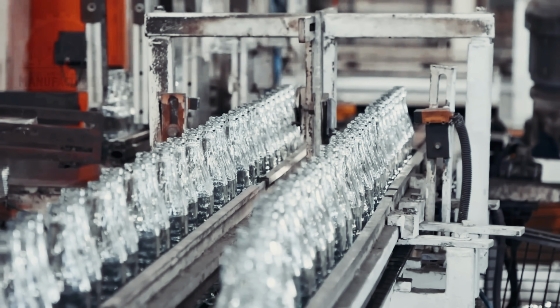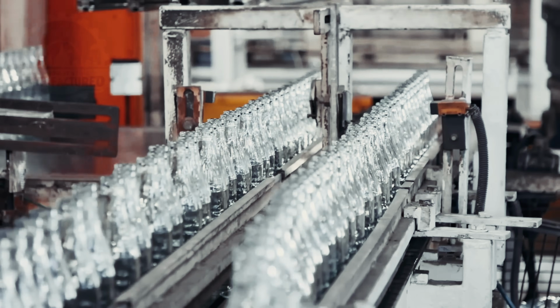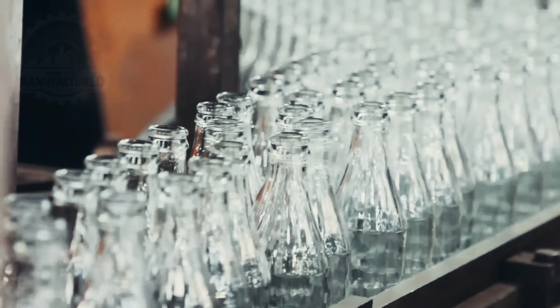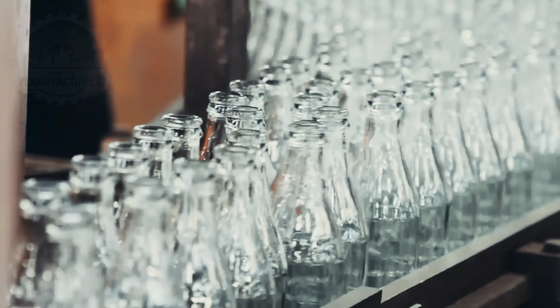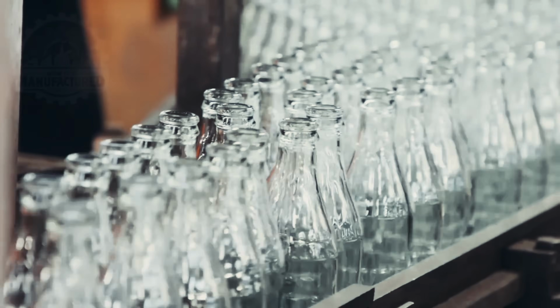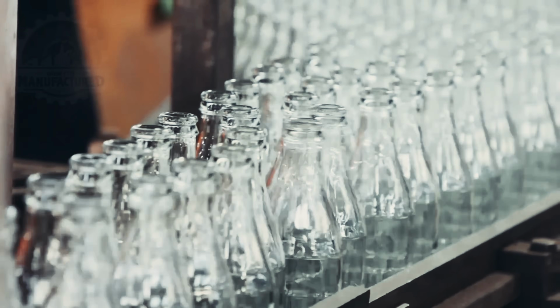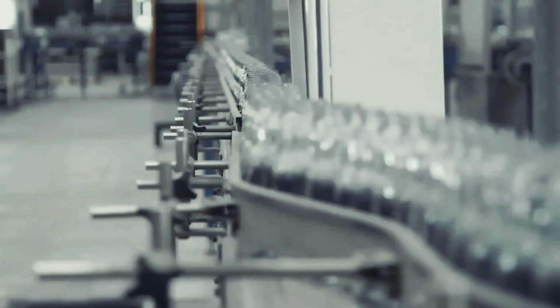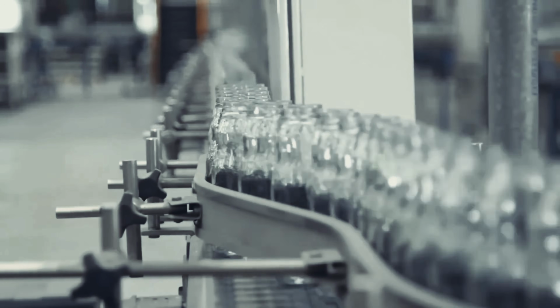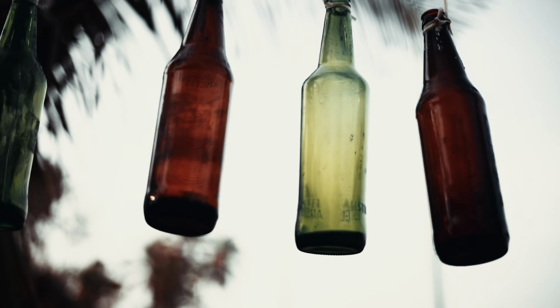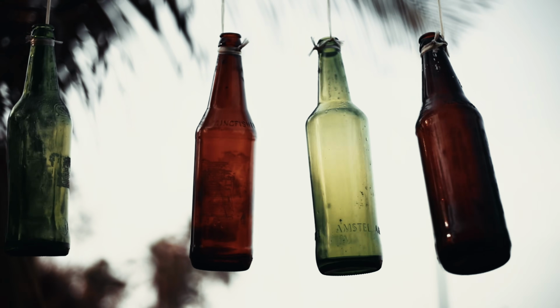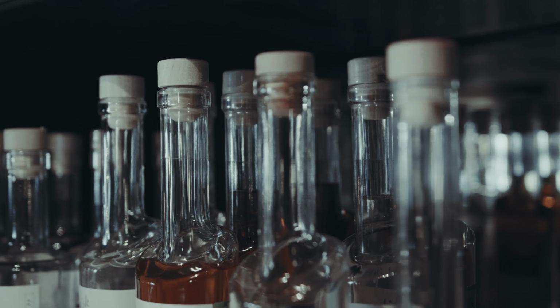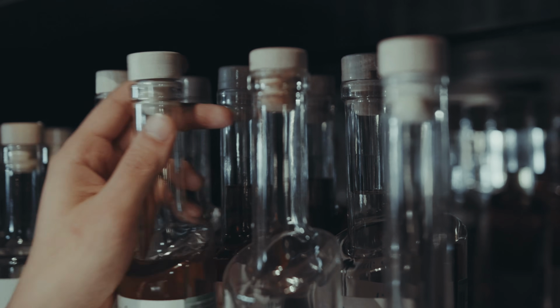Any bottle outside tolerance is immediately diverted, crushed, and fed back into the furnace as cullet before it ever reaches a shipping pallet. The waste rate on a modern bottle line is remarkably low, and what waste does occur never leaves the factory. The bottles pass through their own annealing lehr to relieve forming stress, then emerge cool, smooth, and identical, ready for filling lines that may run just as fast as the glass line that made them.